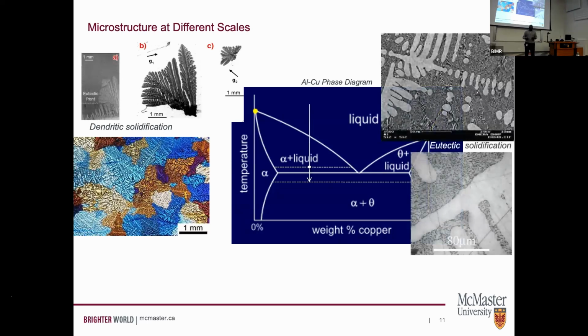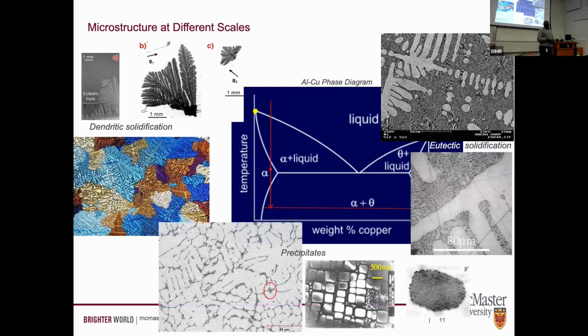If I increase the composition of copper just a little bit, I tend to then get secondary phases that also form. And usually they're forming in the liquid or the interdendritic liquid that formed during the solidification process. If I decide to do something as a function of temperature, so I'm at high temperature first, I form a particular microstructure, then I drop that temperature a little bit, I tend to form these very nice, either faceted or highly anisotropic solid phases within the solid I've already formed.